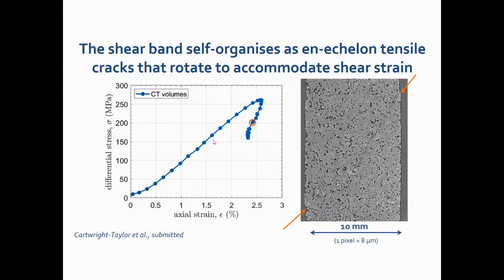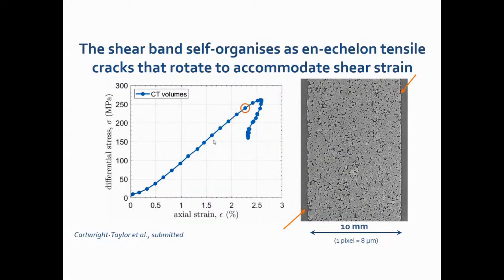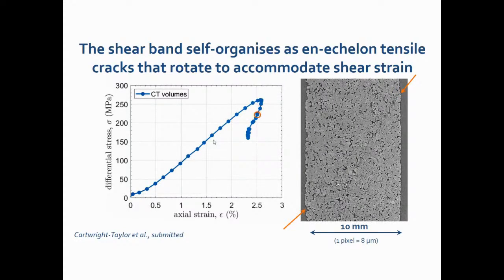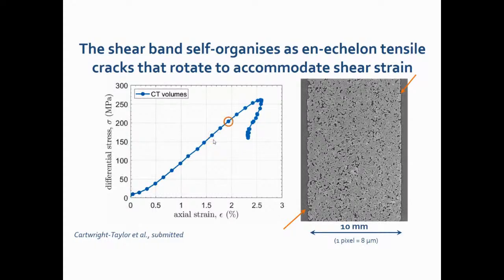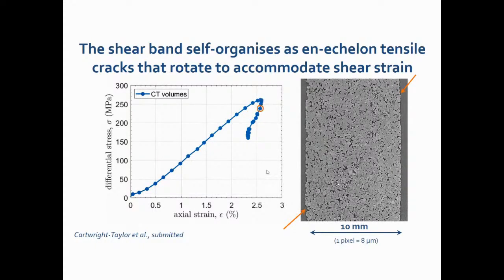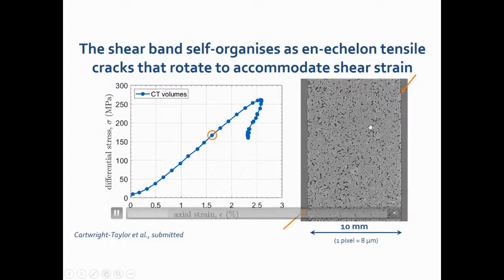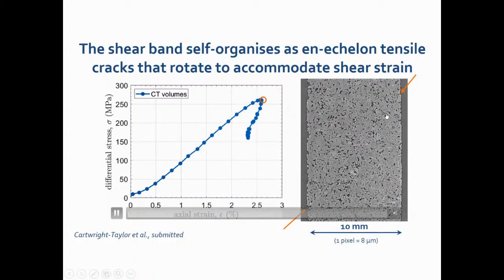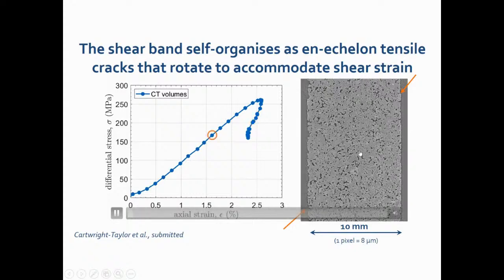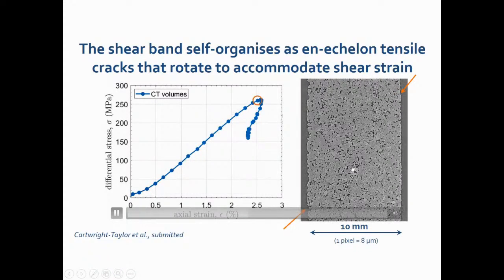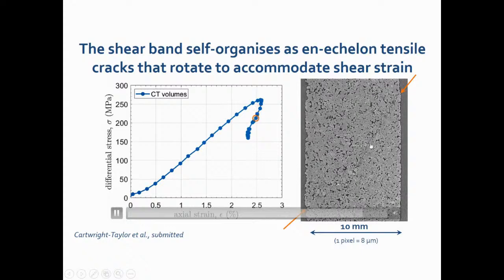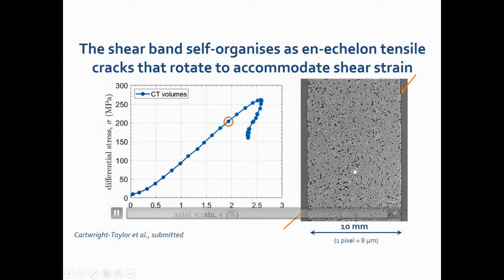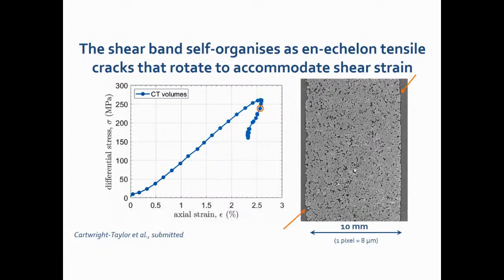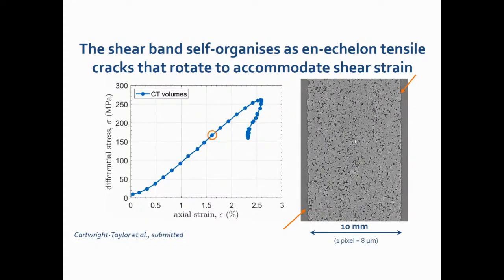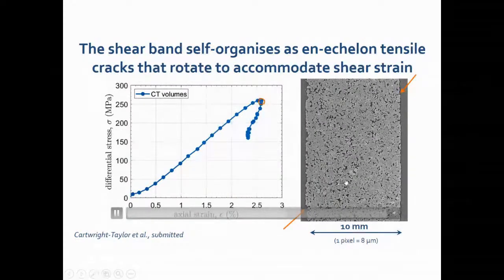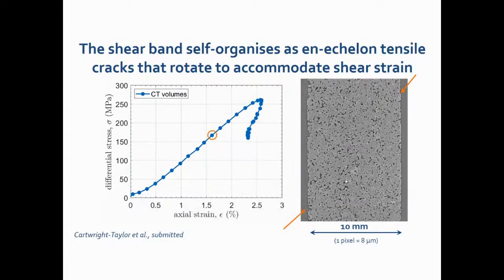Yeah, absolutely. I've been working on this a long time using acoustic monitoring, but it was just a joy to be able to see what this meant. When you see the fault, the shear zone, sorry, it's not a fault yet, just occurring kind of spontaneously, and how quickly it's already self-organized into a shear band. This is a bit different from what we saw with the acoustic emission data. It looked like there was a nucleation and then it grew, and we'll show that that is correct. But there's also this very long shear zone, which is there all the time, which the acoustic emissions were not necessarily picking up.